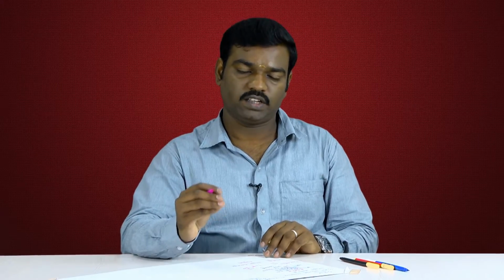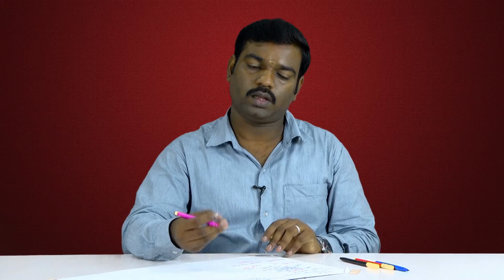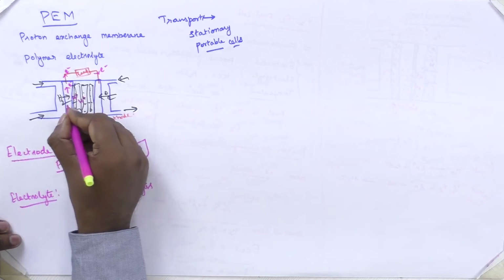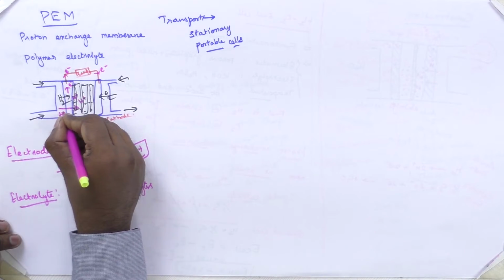In this kind of fuel cell, the Nafion membrane relies on water humidification. Depending on that, the H plus ions move inside the layers of the Nafion membrane. The usage of this Nafion membrane is up to 80 to 90 degrees Celsius, because beyond that temperature the Nafion membrane gets dried. So it is the main difficulty in using these membranes.